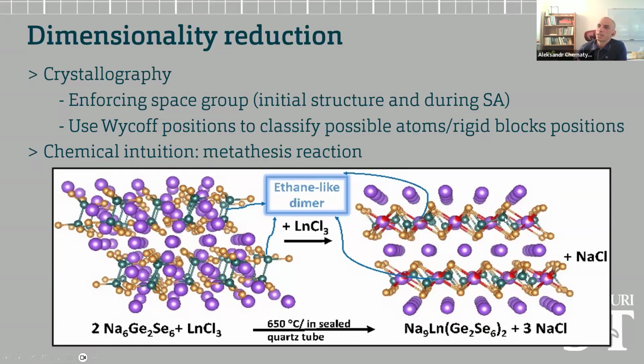But the important portion, again, is that this germanium selenium piece is actually staying in one piece and not really changing its relative orientation of atoms. So we're going to treat this combination of atoms as a rigid block rather than as a molecule, if you will, rather than thinking about that as an individual collection of atoms. And that is going to save us some degrees of freedom. In this particular case, for example, I have 8 atoms, which would nominally have roughly 24 degrees of freedom. I'm trading this in for 3 degrees of freedom associated with the motion of the rigid block and 3 degrees of freedom associated with rotations. So I hopefully achieve some reduction.